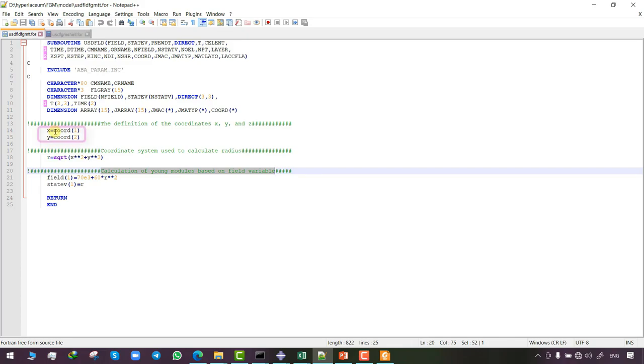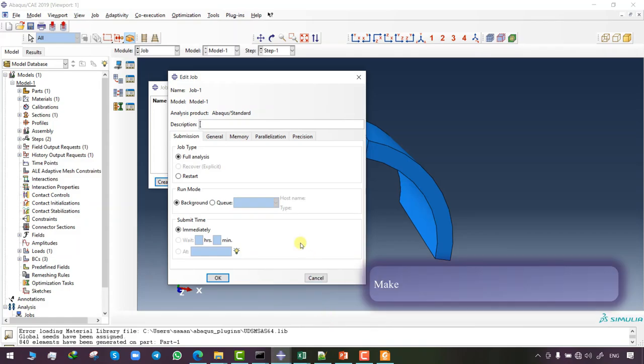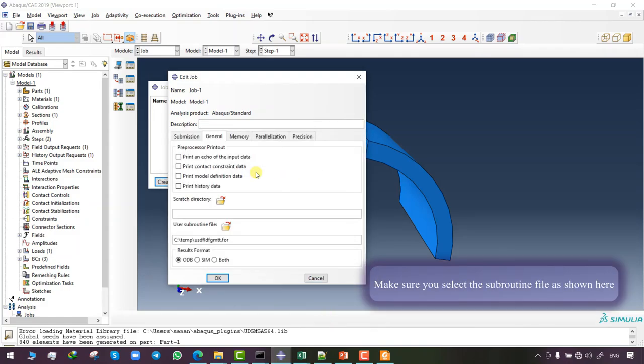Before running the job, let me explain how the coding works. Our first coordinate is defined as X and our second as Y, so we don't need to enter coordinates multiple times throughout the code. We calculate the radius using the coordinate system, then define Young's modulus based on the field variables and store the radius in STATEV — which, unlike field variables, is not memory-less. After submitting the job for analysis, we view the output in the Visualization module.